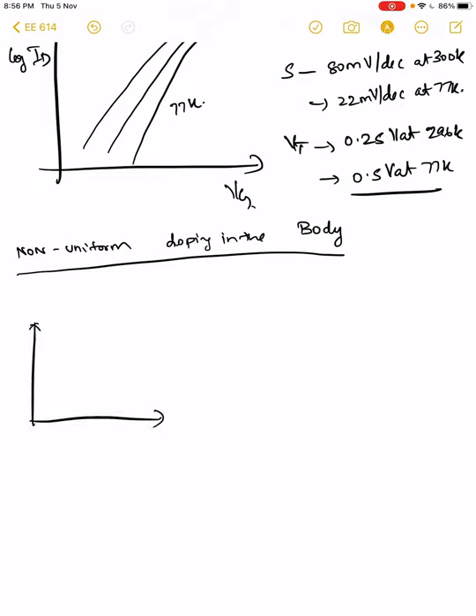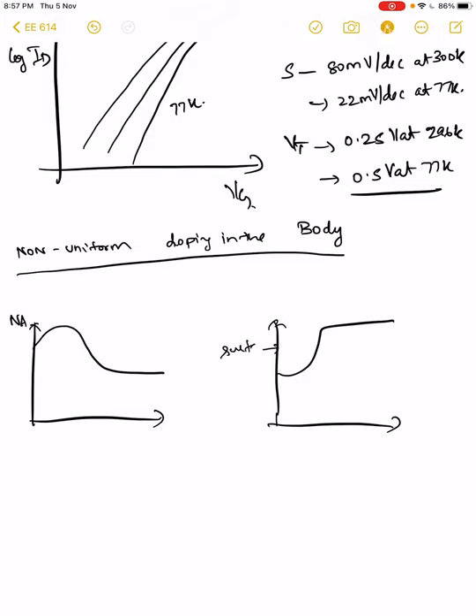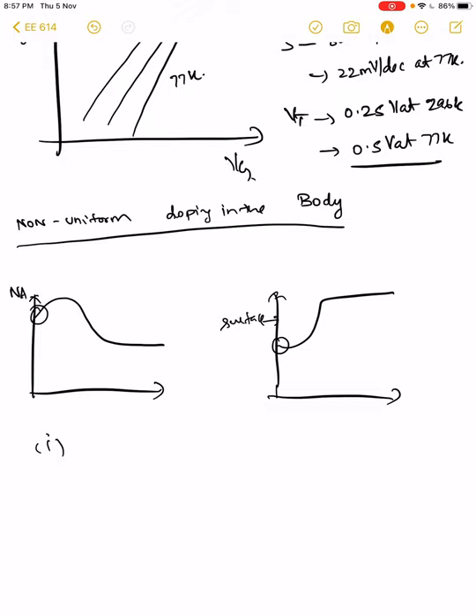So we are talking about the doping density from the surface. They are either doped in this particular fashion or in this particular fashion. Let's say this is the surface. Either the surface is doped very low and then you have a little higher doping in the body, or you have some very low doping in the body and then the doping increases close to the surface. But then at the surface, there is always a small reduction in the doping density. Why? So here you see you have a lower doping density at the surface, right? This is called a high-low profile, and this is called a low-high profile.